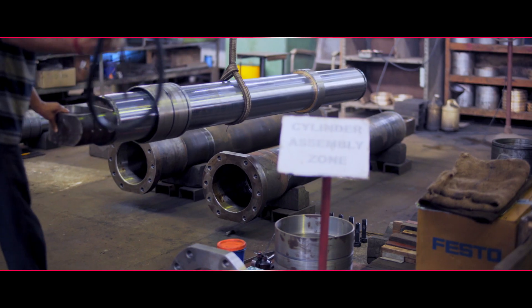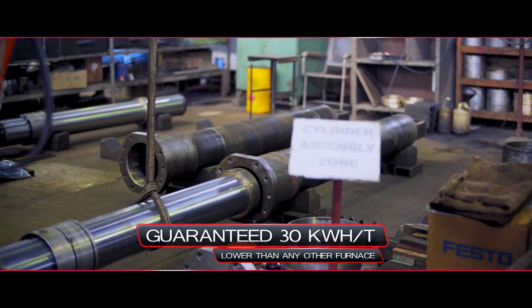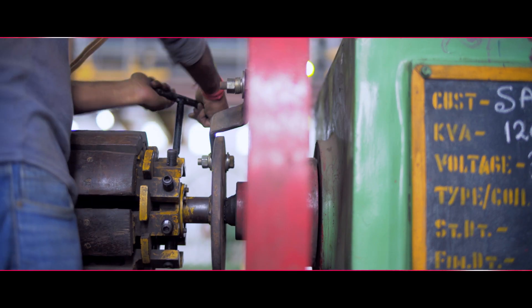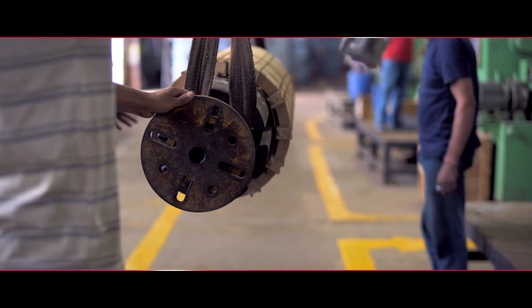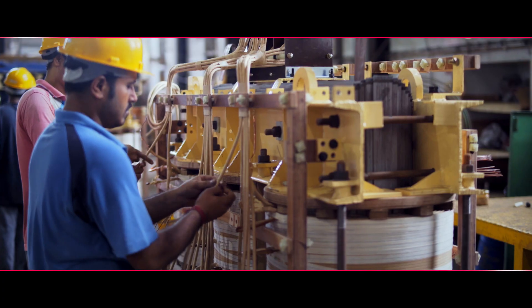In little over a year and a half, we have received orders worth over 11 million tonnes per annum capacity addition. With the green furnace, we are guaranteeing 30 to 40 kilowatt hours per tonne lower than any other make. Considering 99% yield and 1,600 degrees tapping temperature, we have achieved 470 kilowatt hours per tonne in scrap-heavy regions like Mandi Gobindgarh, Western India, Pakistan and Bangladesh.